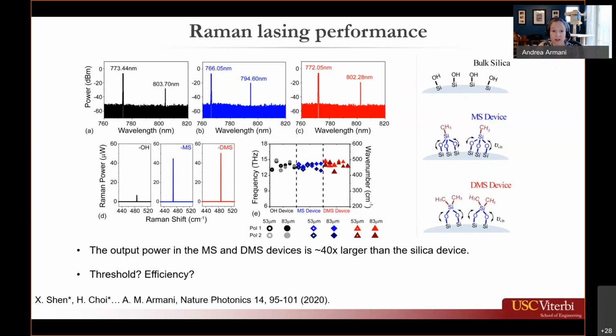And then it becomes very apparent that there's an improvement when you have a methyl or dimethyl coated device. Additionally, the Raman shift was nearly identical, which indicates that it is that Si-O-Si bond that's generating the signal. When we plot all of the data from all the devices, you can see that the Raman shift is nearly identical. Additionally, this Raman shift falls within the expected range for the Si-O-Si bond, which indicates that this is due to that surface chemistry and not due to some other phenomena.